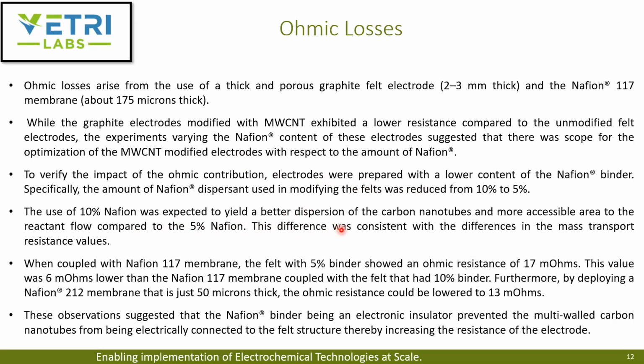So this difference was consistent with the differences in the mass transport value. Because mass transport value was higher for the 10% and lower for the 5%. But the contribution is very low and it's mostly on the ohmic resistance. So what they identified is when they coupled it with Nafion 117, the felt with 5% binder showed an ohmic